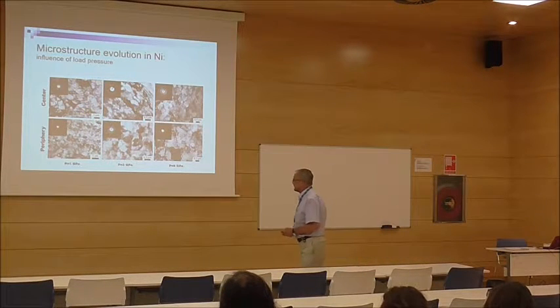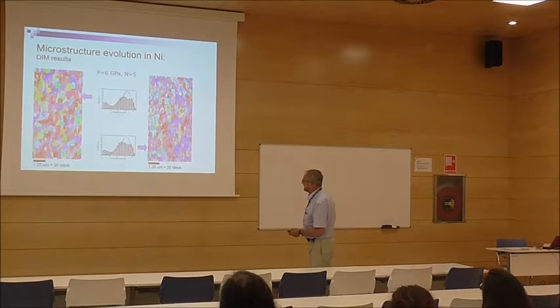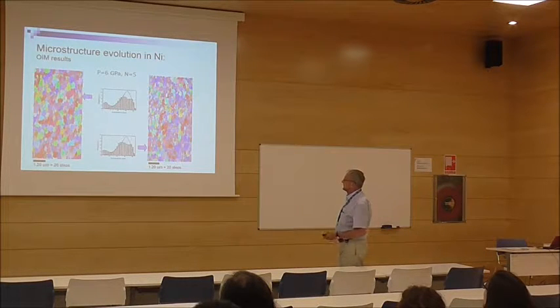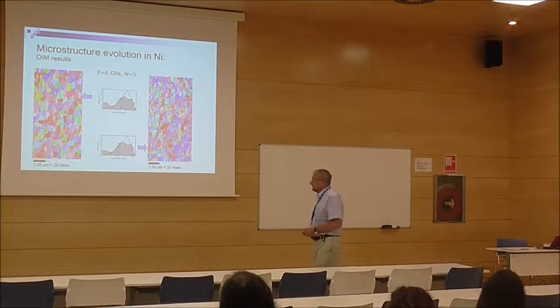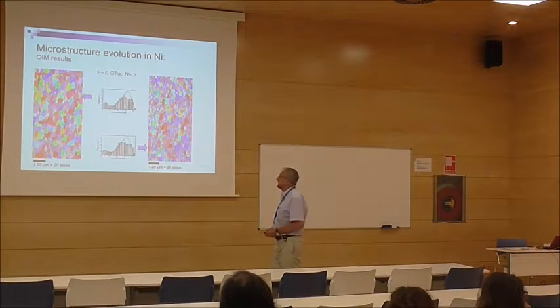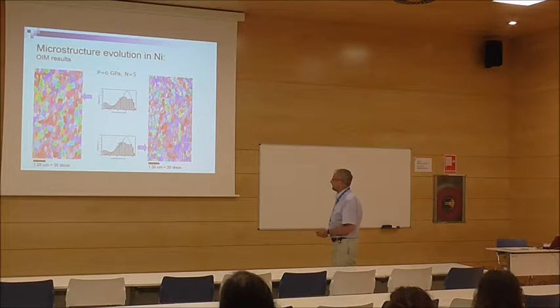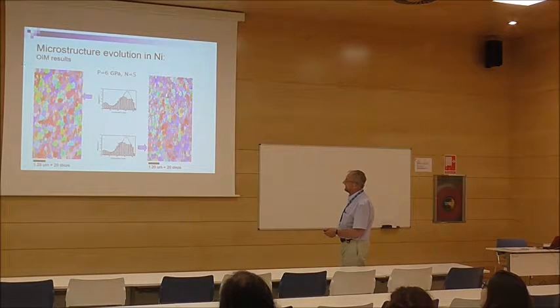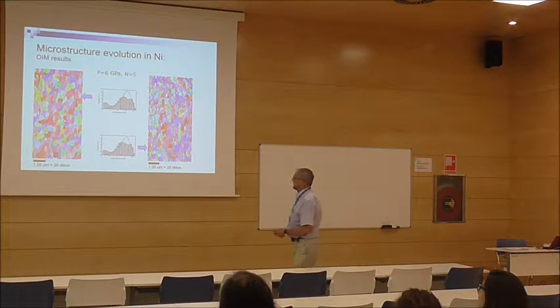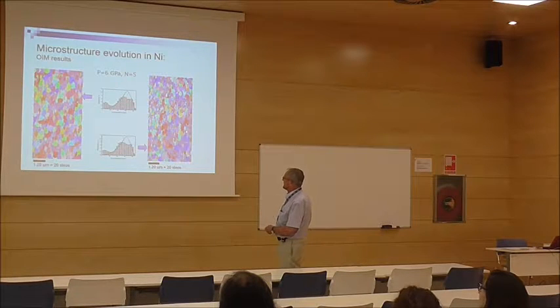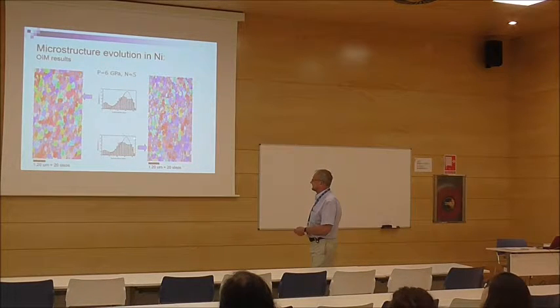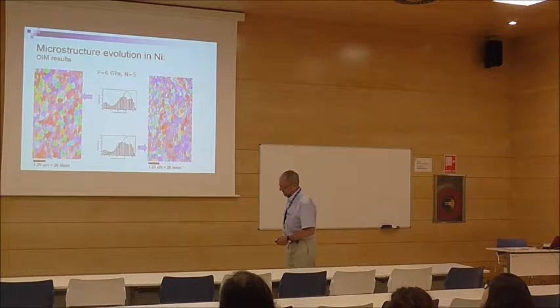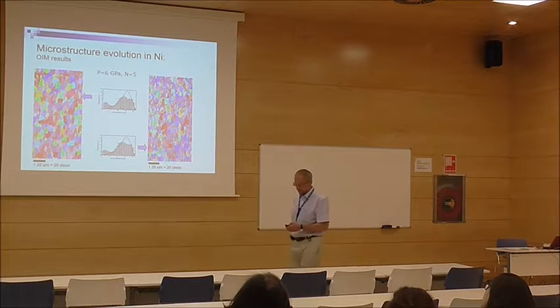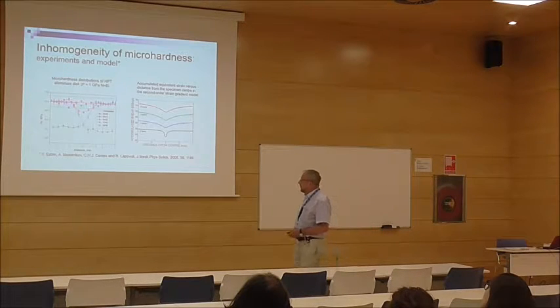This is the microstructure. I will not stay on it. And this is also the first time using EBSD to characterize nickel, in the HPT nickel, showing the microstructure at the center and at the edge. So you see quite similar microstructure, and the misorientation distribution function is also similar, but if you look carefully, there is some slight difference between them.